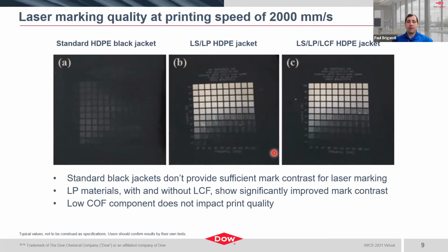The one thing that we didn't cover in this paper, and we actually covered in a previous paper as we get into looking at laser print, is that we are also able to introduce the UV performance. So we are able to maintain UV performance in the field, even though these materials will contain less than the 2.5% carbon black that's typically used. And so that was the topic of a previous paper.